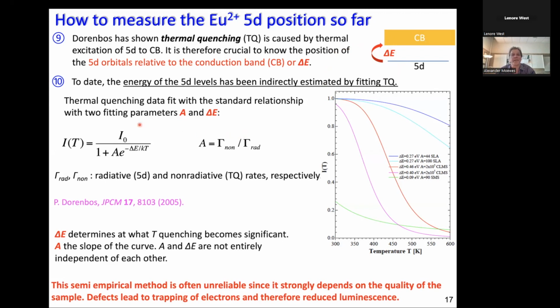It's a simple function which depends on the temperature, on the Boltzmann constant, and on delta E. And delta E is the distance from the 5D to the conduction band. These were emulated curves in Origin with this model, but the bottom line is when you measure the thermal quenching, the decay of the luminescence with temperature, you can use a fit to derive delta E. This was how delta E, the distance from 5D to the conduction band, was up to date evaluated.